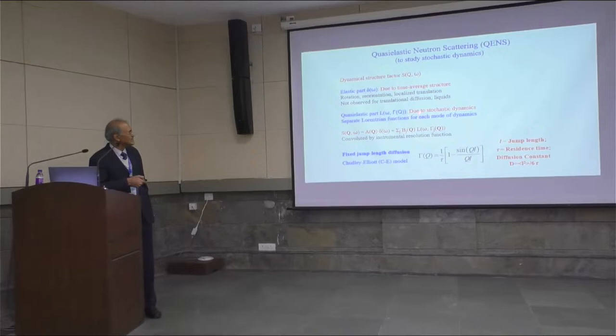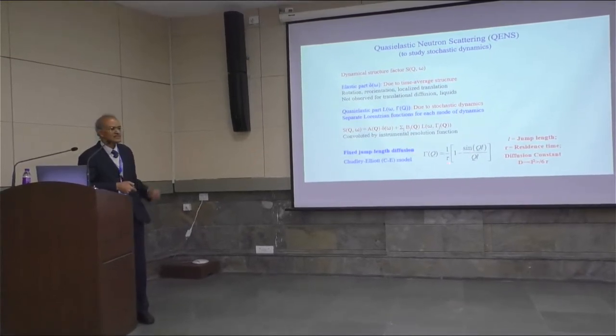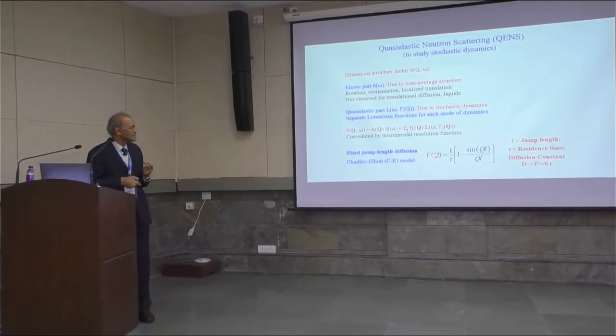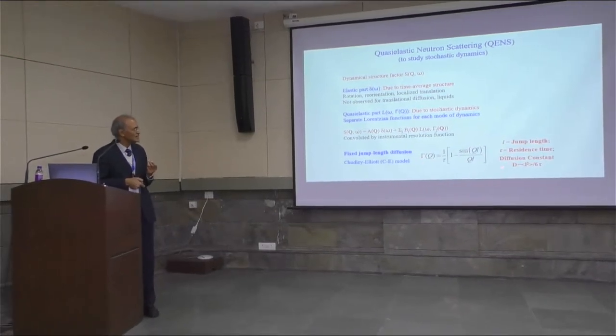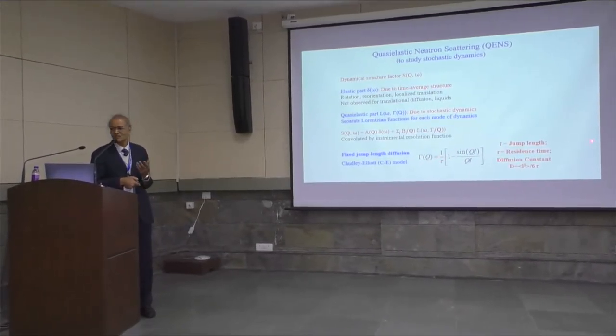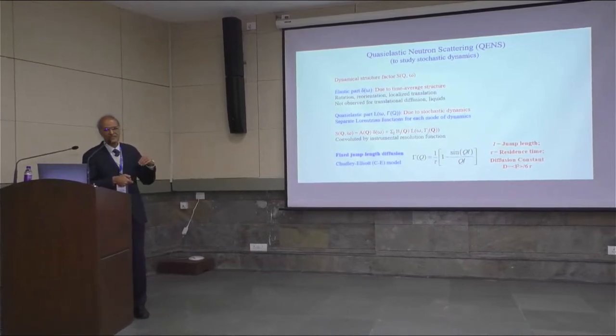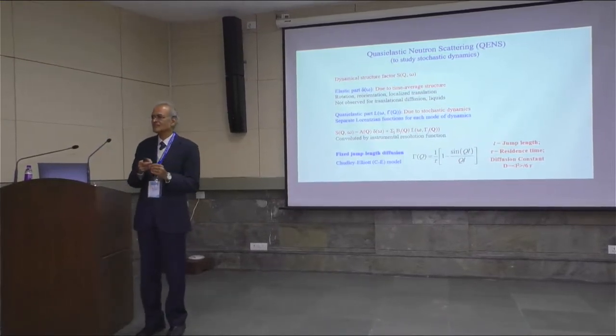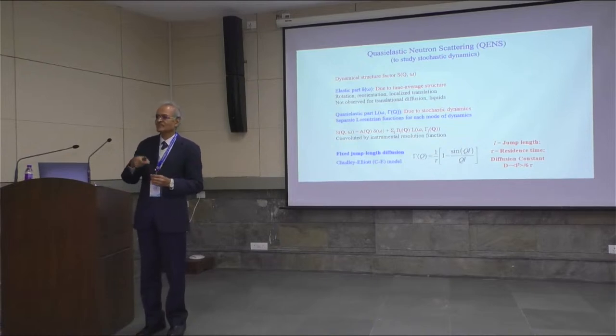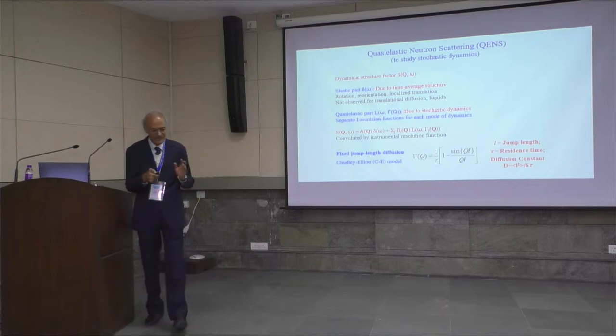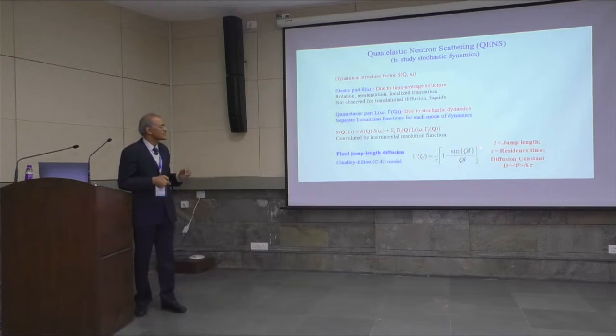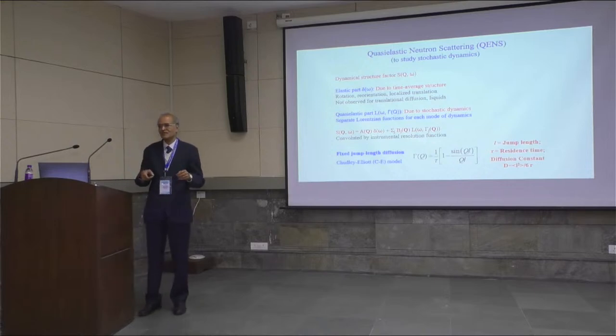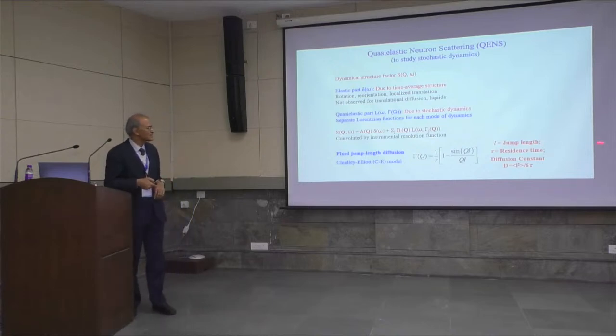Then the width of the Lorentzian function, that is, the width of the broadening of the elastic line as a function of the momentum transfer, can be related to certain models. This is one of the simplest models. In a crystal lattice, atoms do not diffuse exactly like a liquid. They may be jumping from site to site, and there is a certain time it takes for a jump. So typically one can think of a jump length, and a residence time between two jumps, how long the atom stays at one place on average. This is stochastic, so these are not fixed numbers. And then the diffusion coefficient can be found by such relations.